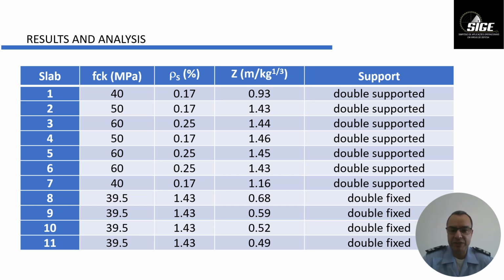You can see that for slab 10 and slab 11, the difference was actually the scaled distance. Slab 11 has a lower scaled distance, and slab 10 a higher scaled distance. So a higher scaled distance brings less damage than a lower scaled distance.